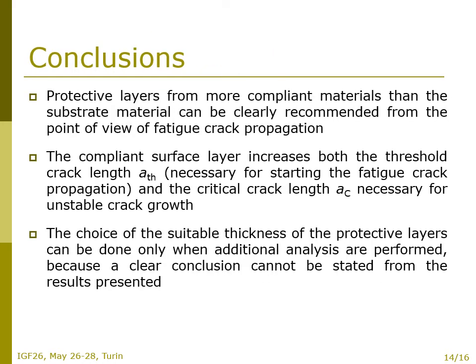Thus, more general conclusions can be stated. Protective layers from more compliant materials than the substrate material can be clearly recommended from the point of view of fatigue crack propagation. The compliant surface layer increases both the threshold crack length, ATH, necessary for starting the fatigue crack propagation, and the critical crack length, AC, necessary for unstable crack growth. The choice of the suitable thickness of the protective layers can be done only when additional analyses are performed, because so far a clear conclusion cannot be stated from the results presented.